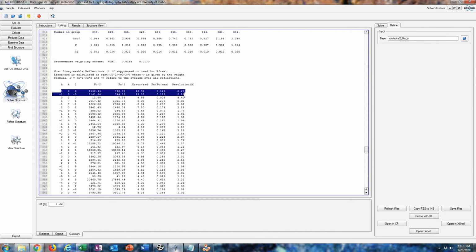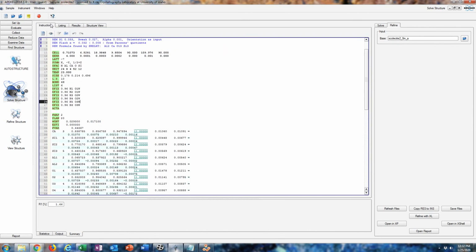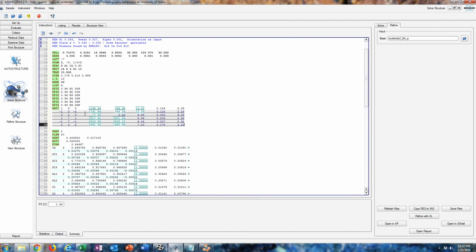These disagree with our model due to maybe disorder or periodic disorder. But we can just get rid of those, if they are just from a little inclusion in the crystal or some defect in it. You can get rid of those reflections by using the OMIT command and entering the HKL of those reflections. Just paste them.